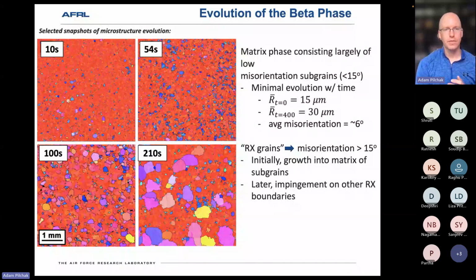All right, so here's a couple snapshots of the evolution over time. It's just 4 of them, at 10 seconds, right around a minute, 100 and 210 seconds. And so what we found was that at early stages, even as early as 10 seconds, we saw some fraction of grains that had recrystallized. The subgrain size at that time was around 15 microns. Average misorientation was around 6 degrees in those subgrains. With additional annealing time, you get a larger fraction of recrystallized grains.